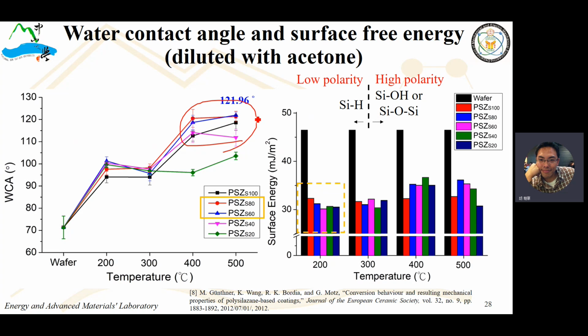And so we can predict or speculate that for the temperature below 300 Celsius, the silicon hydrogen bond is formed with low polarity. When the cross-link temperature is higher than 300, it's high polarity. It's silicon hydroxide or silicon oxygen silicon.